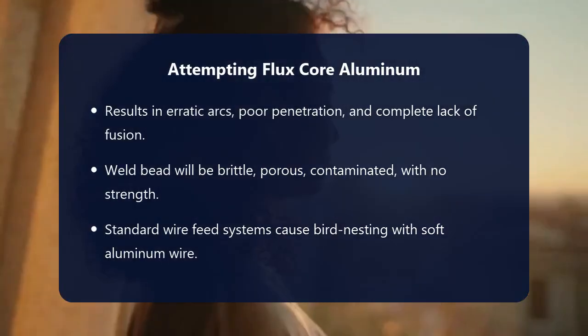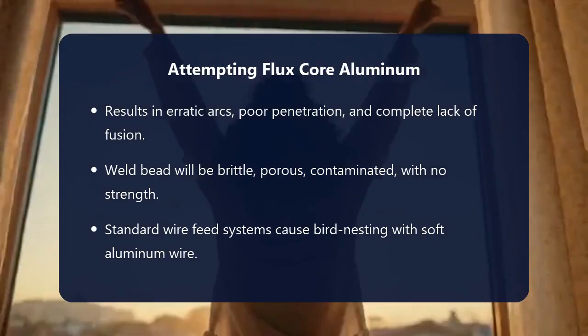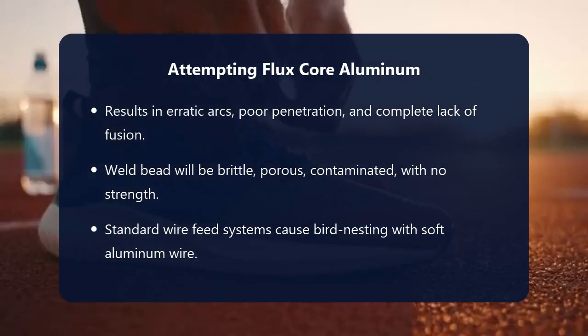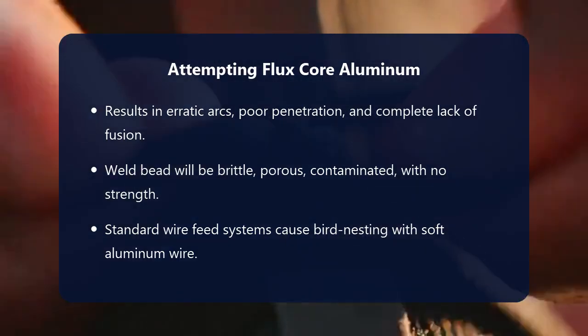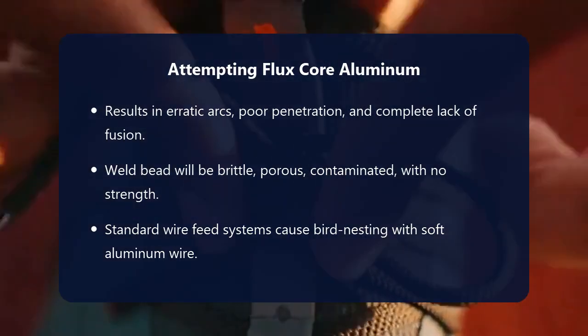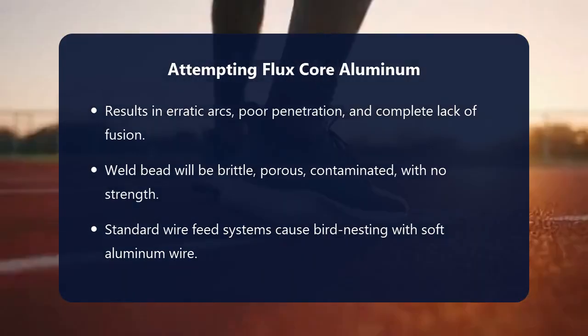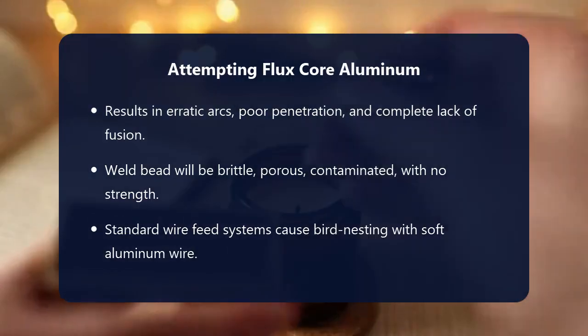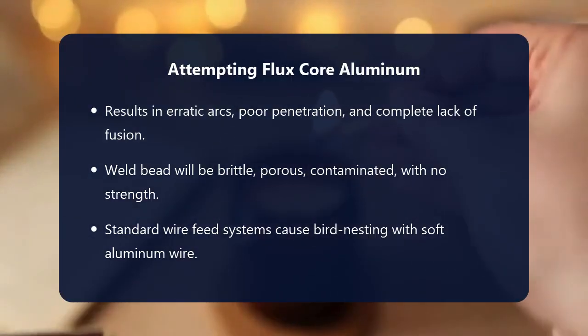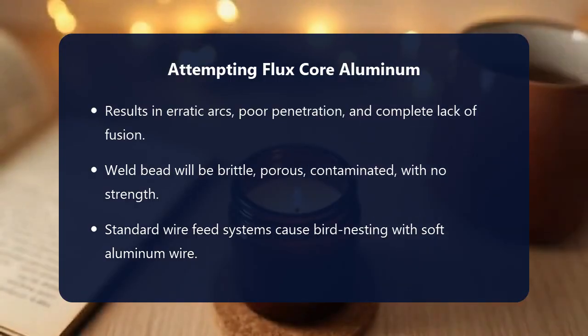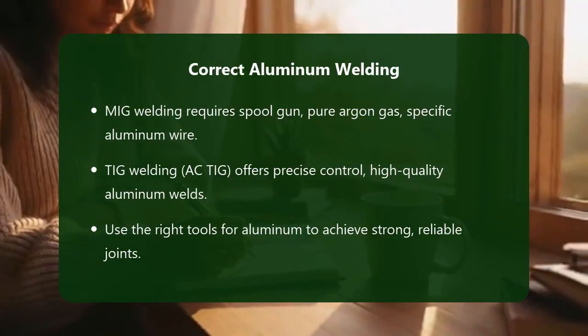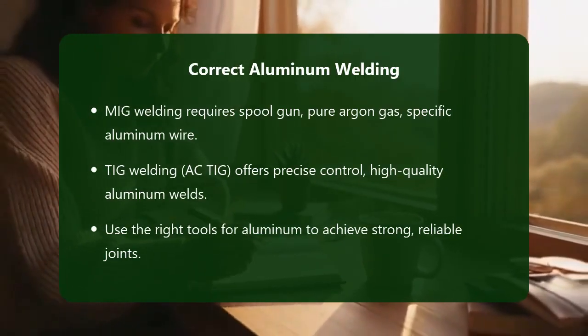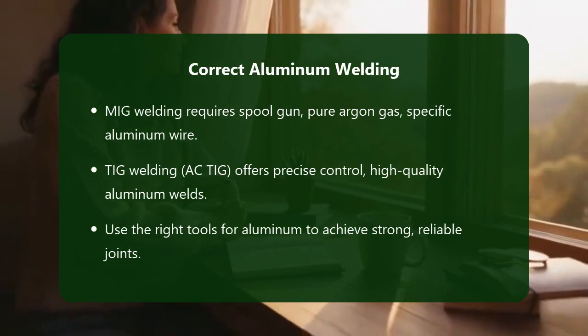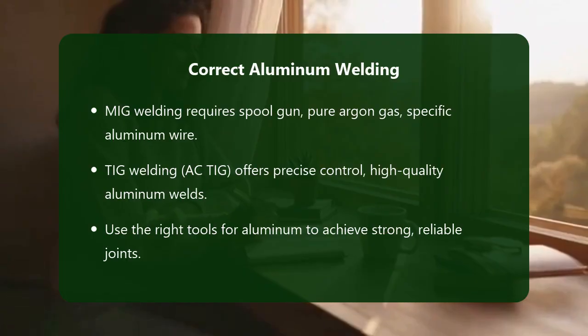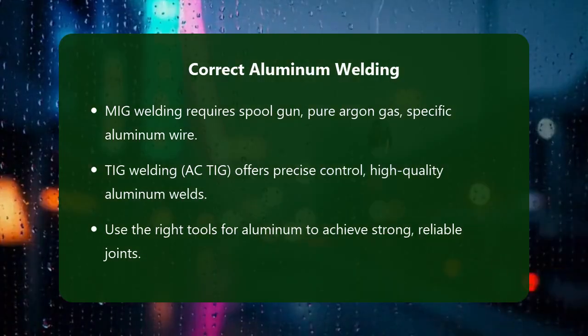So, if flux core isn't the answer, what is? For welding aluminum, you typically need one of two primary processes: MIG welding with a spool gun or TIG welding. For MIG welding aluminum, you must use 100% pure argon shielding gas, special aluminum MIG wire, like 4043 or 5356 alloy, and preferably a spool gun. A spool gun minimizes the distance the soft aluminum wire has to travel, preventing feeding problems. The argon gas provides the inert atmosphere needed to protect the molten aluminum from oxidation.